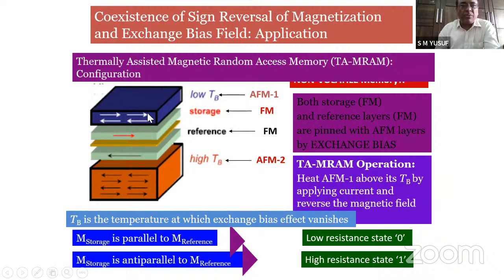For that, one has to break this exchange coupling. But in our case, as you could see, by varying temperature, one can get the magnetization reversal. That means if you pass DC current, there will be Joule heating, and Joule heating causes the temperature to change across the compensation. The magnetization will flip, and you will get the other state. So above compensation one state, below compensation another state.